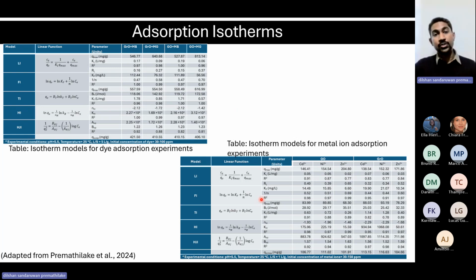And then we evaluated the adsorption isotherms, again using 5 different isotherms: the famous Langmuir and Freundlich, and then Temkin, Halsey, and Harkins-Jura. We identified that both the dye adsorption and the metal adsorption follow the Freundlich isotherm. This tells us that this material has heterogeneous surface active groups, and the affinity of the dye pollutants and the metal pollutants is completely different from each other. This is why they follow the Freundlich isotherm model rather than the other models that we evaluated.